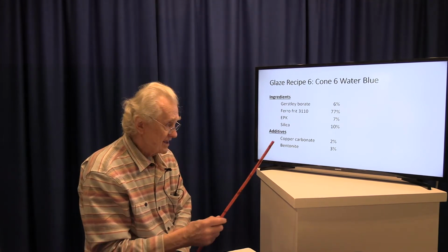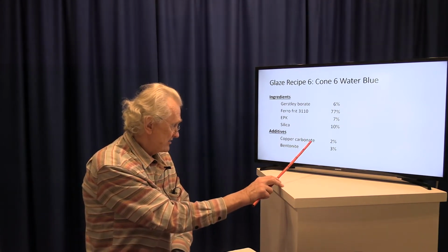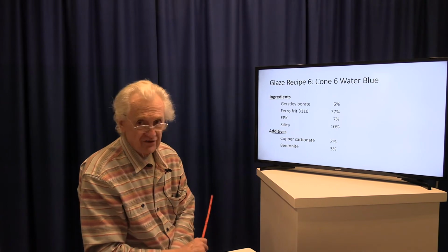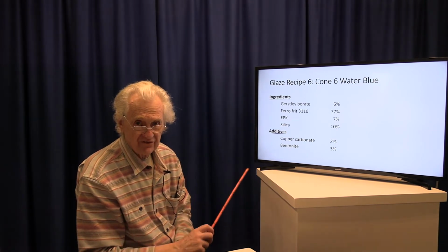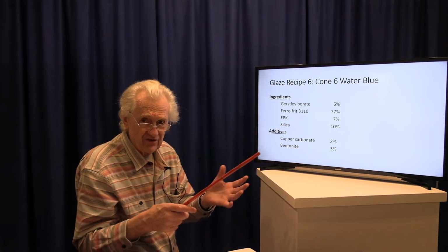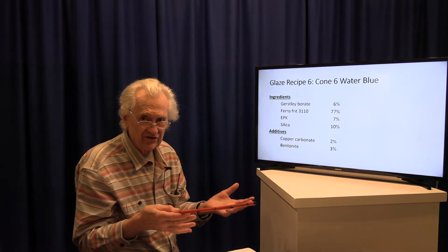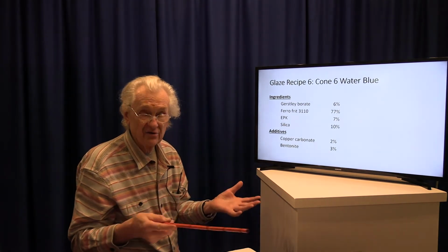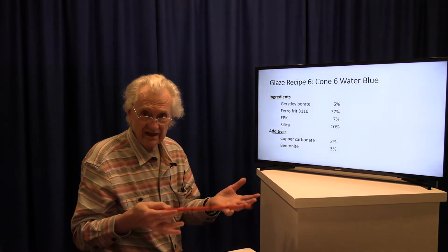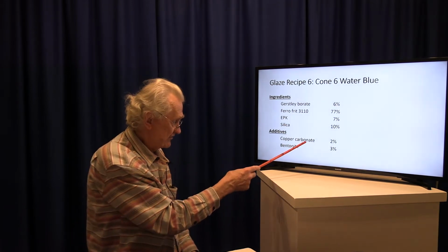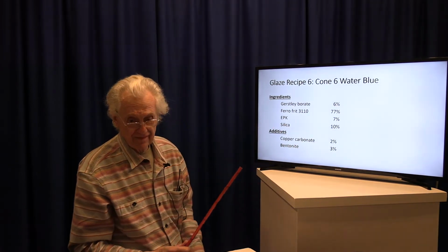Which means that even though the carbonate is low, because it's crazing, it may also not be food safe. Because when the glaze crazes, it opens up all these cracks where now the material could possibly, not definitely, but possibly leach out of the glaze. So it may not be food safe because of the crazing. Okay? Okay, and let's go to another one.